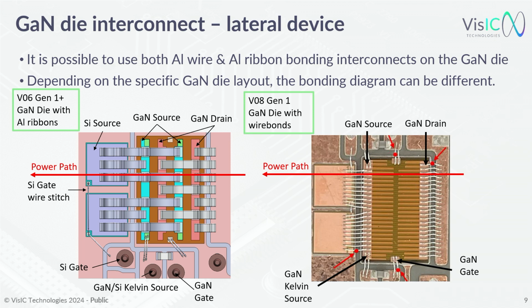But now we are changing also the methodology. So we take at the surface, we take now source, drain, in order to reduce, first of all, the RDS on of the device, but also increase the ampacity of the device. So with the same chip size, we basically get around 35-40% more current out of the same cell structure. So even we are not changing the design of the chip itself from the cell structure, just by redoing the RDL layer and redoing the organization on the surface of the device, we can improve the device properties by more